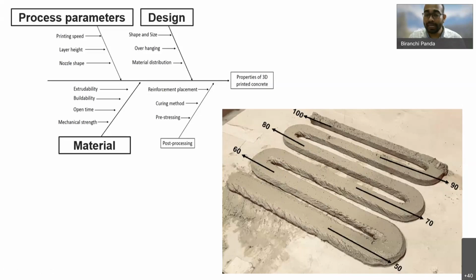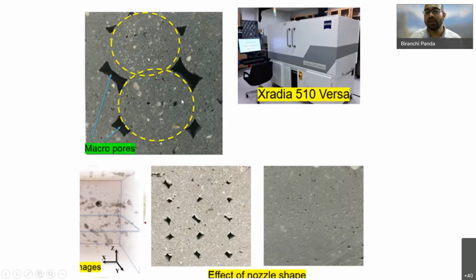Sometimes, depending upon the nozzle shape, we also get different properties. For example, if you're going to use a cylindrical, circular nozzle, you're going to end up with this kind of porosity. But now if I have a square nozzle, I can have a more compact structure. Again, one more point I would like to highlight here is that in concrete printing, the nozzle shape is not the only important point; the material is also important. Because whatever picture you are seeing here, this is a very stiff material. So you can see even after printing, it remains its shape exactly the same as the nozzle diameter.